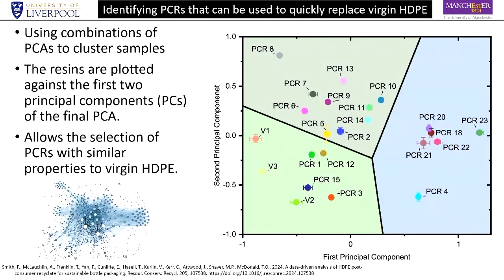So here we can see on the right, that clustering analysis. And essentially what we've done is, by looking at all the different features in the material, we can identify which features allow the material to be separated. So in this bottom area here, we've got our virgin samples labelled with V's, and then we've got other PCR samples that are very similar to these. So essentially, if you were trying to produce a high quality PCR, you'd be looking to have it in this section. And if you were trying to select a PCR to put into packaging, these materials would probably be the quickest to substitute in for virgin plastics.